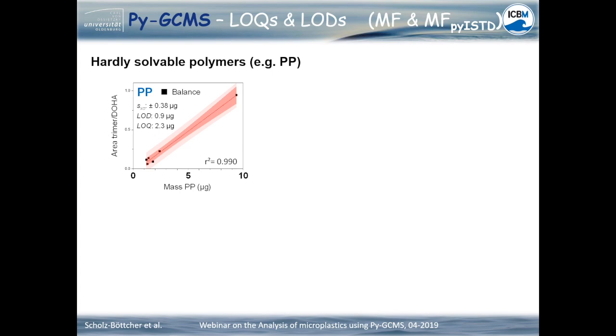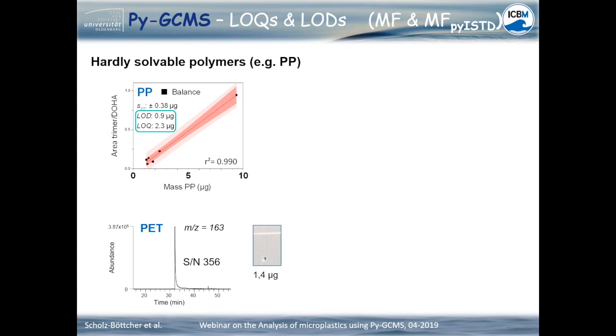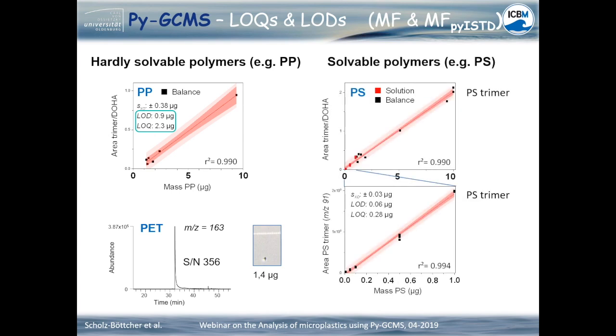For hardly solvable polymers, shown here for polypropylene as an example, the LOQ and the LOD estimated using the calibration function only are around 1 microgram. But regarding the signal to noise ratio, 1 microgram is not the detection or quantification limit, here shown as an example for polyethylene terephthalate. Working with solvable polymers, much lower limits are available, as shown for polystyrene.